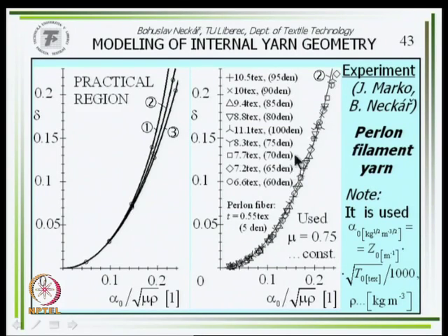You can see that all different counts, all different twists, are lying on only one curve. Using packing density 0.75 in our equation, this continuous line shows the curve according to our theoretical model. The comparison is excellent. It's the best in my life, the comparison between experimental results and the theoretical curve. So perfect it is. But